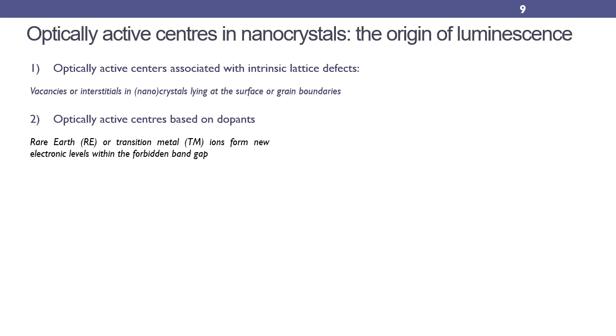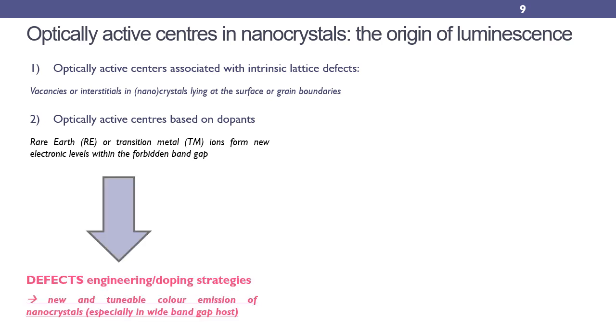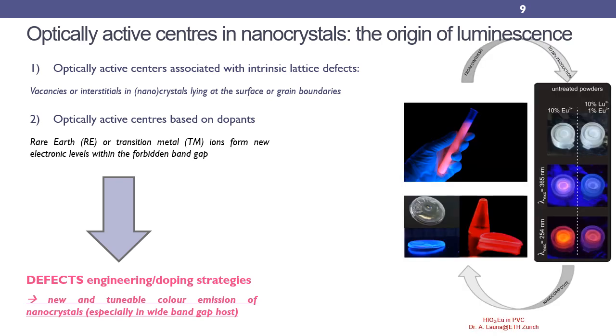Nowadays, the investigation of the luminescent nanomaterials aims also to the development of new defects engineering strategies and doping routes. In it, the application of both strategies enables to obtain nanomaterials with tunable color emissions. This is an example of hafnium oxide nanoparticles doped with europium. The blue color under near UV excitation is related to intrinsic defects. In turn, when the excitation is at higher energy, the europium emission is activated by charge transfer mechanism.